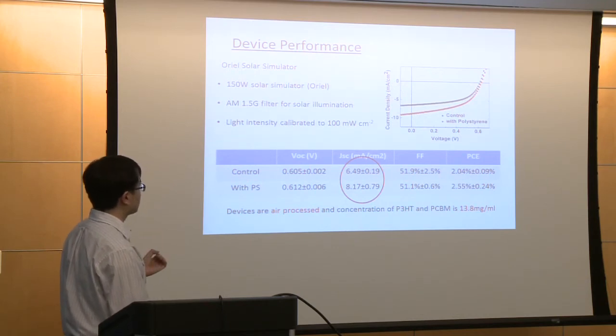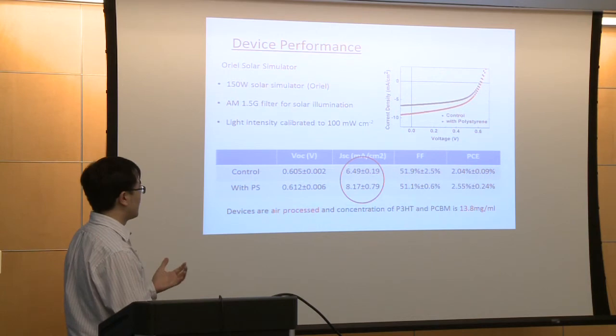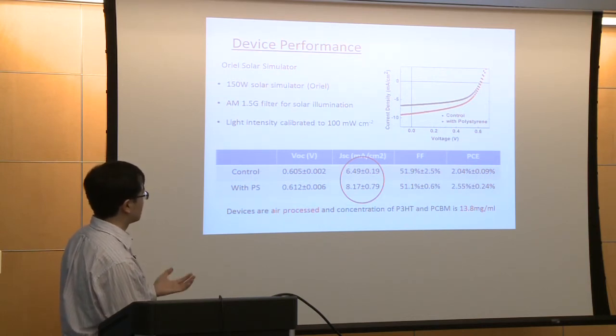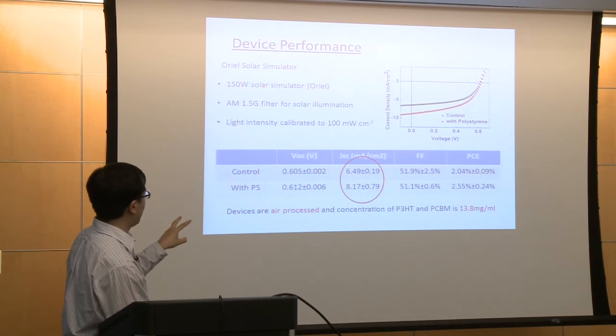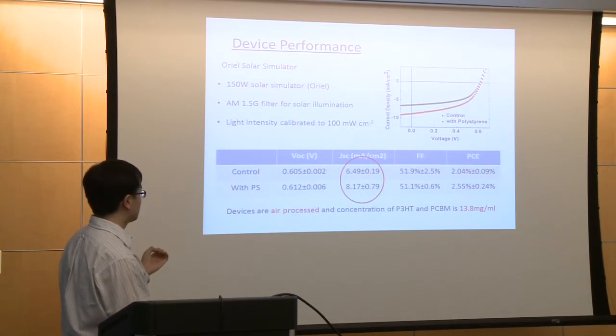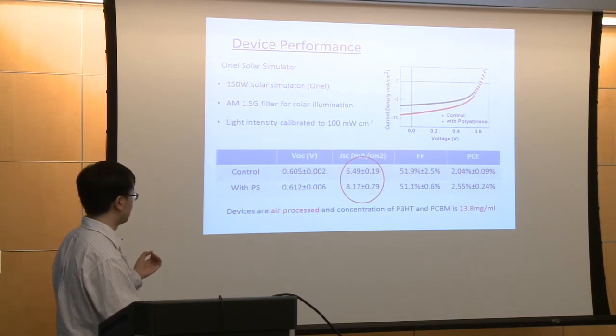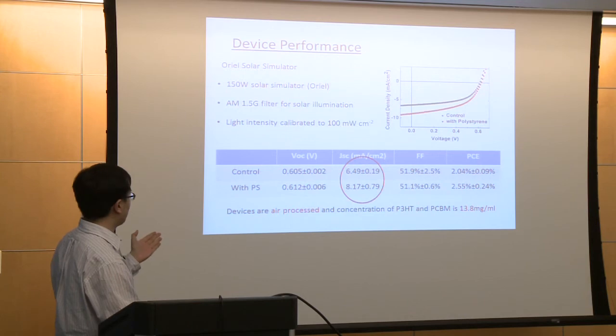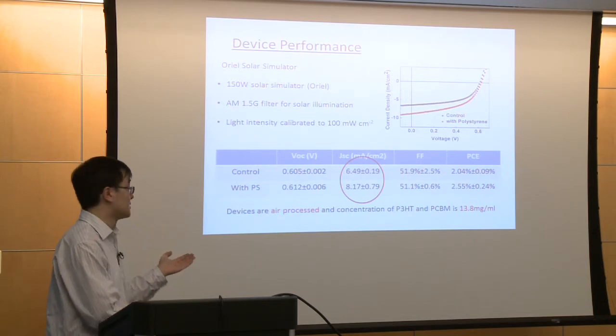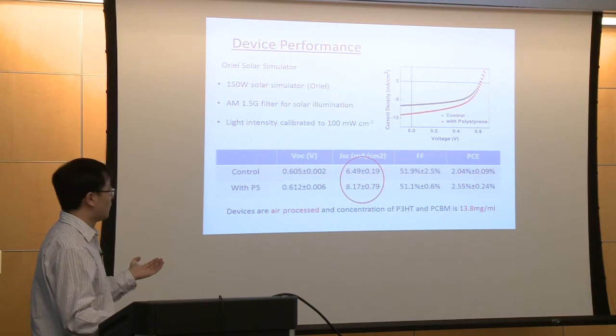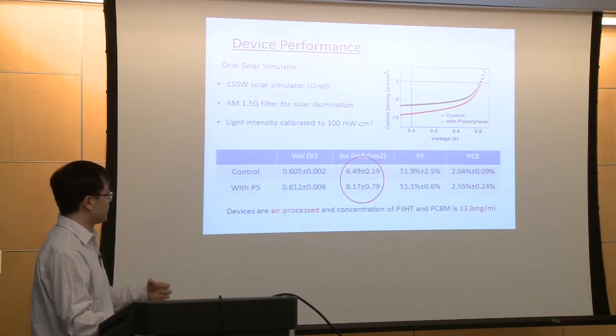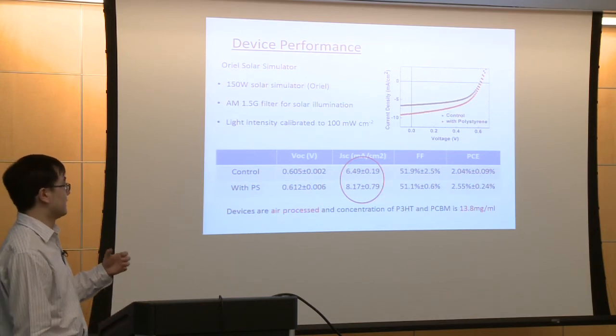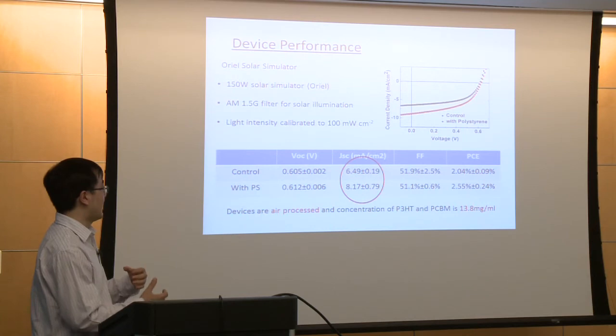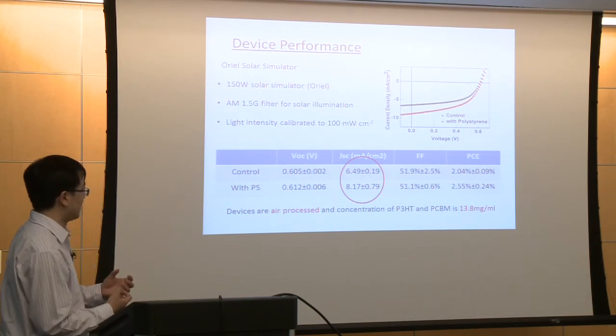So here are our results. We can see the power conversion efficiency, which is PCE, is increased by about 25% by introducing our column structure into the active layer. Comparing the different parameters, VOC is the open circuit voltage, JSC is the short circuit current density, and FF is the fill factor. We can see there's not that much difference for the open circuit voltage and the fill factor, but we can see a significant enhancement for the short circuit current density, which means this column structure really improved the charge carrier transportation within the active layer. So this can enhance the current density of the solar cell and then enhance the efficiency.